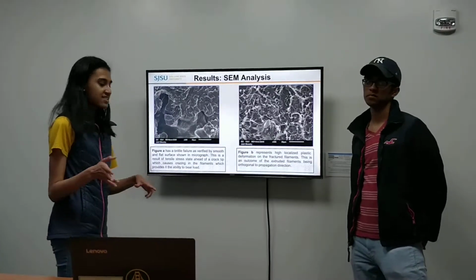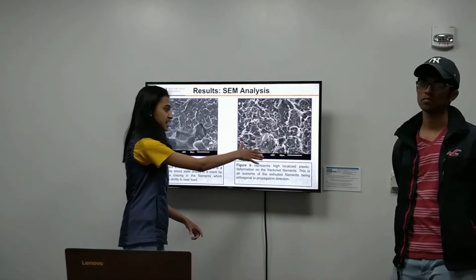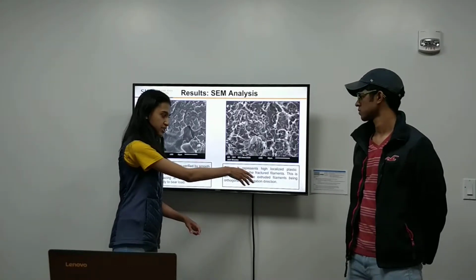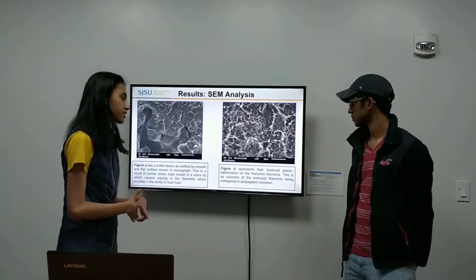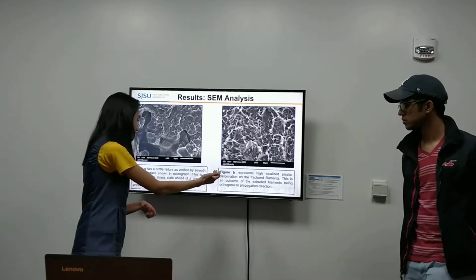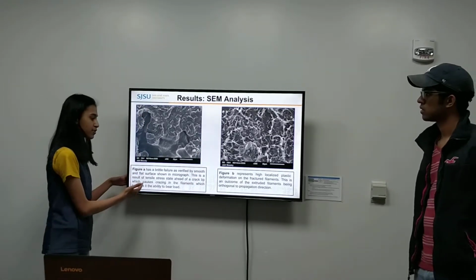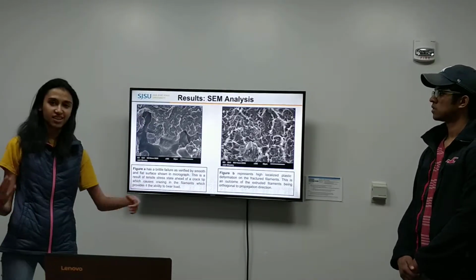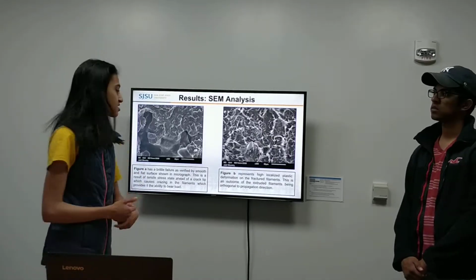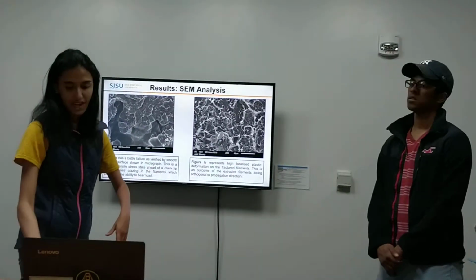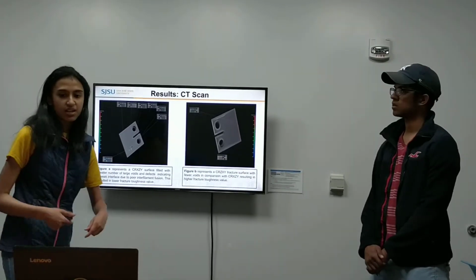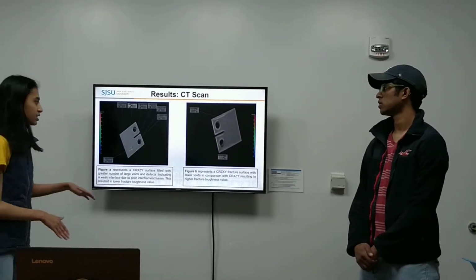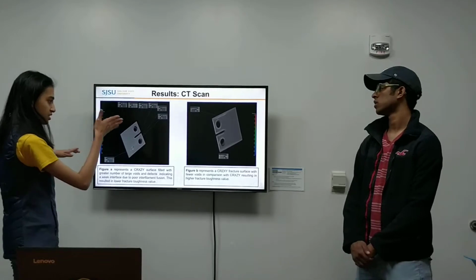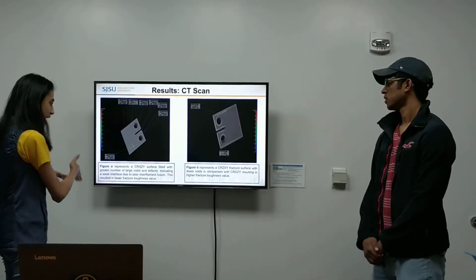and AFO casts. So the crazing here is in the filaments. To conclude our SEM analysis, ZXY produced ductile fracture, which means it has higher fracture toughness, and CRAZY produced brittle fracture, which means that it's not suitable for medical devices and it produced lower fracture toughness values. And then CT scanning. You can relate this analysis to the SEM analysis.